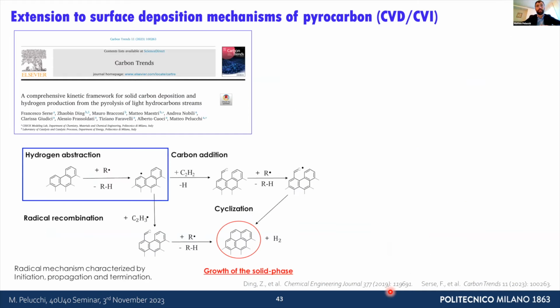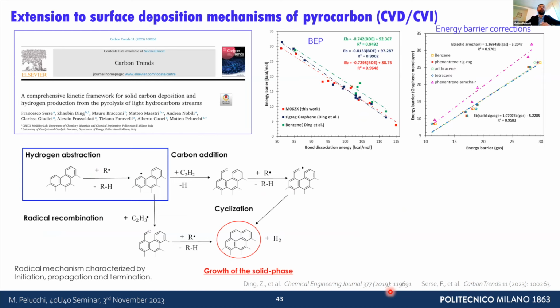So we've extended this to describe chemical vapor deposition phenomena. The reactions are basically the same that lead to the growth of soot particles starting from aromatics and PAHs and so on. We get the HACA mechanism, radical recombination, resonance stabilized radical addition and recombination, cyclization reactions. This leads to the growth of the solid phase.